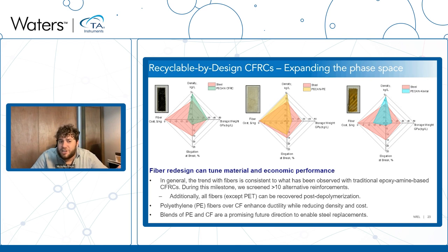So on the left is our carbon fiber composite that I've shown you before. In the middle, we make a polyethylene-based composite, so we use polyethylene as our reinforcement. You see that when we compare our storage modulus to the weight ratio here, we take a huge hit, but we're increasing the elongation at break of these materials themselves. You can use Kevlar itself, but it doesn't really get the benefits, at least in this application, compared to carbon fiber.